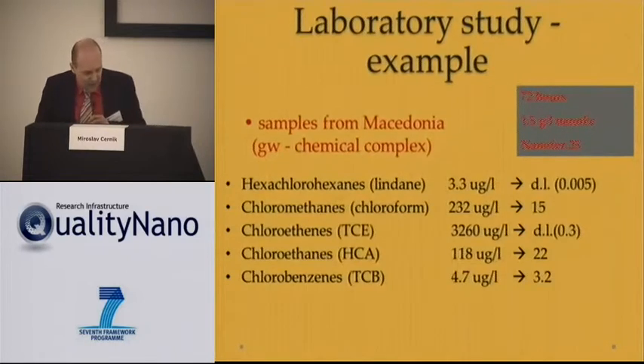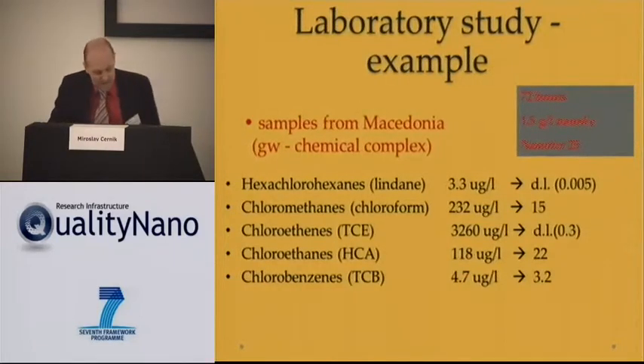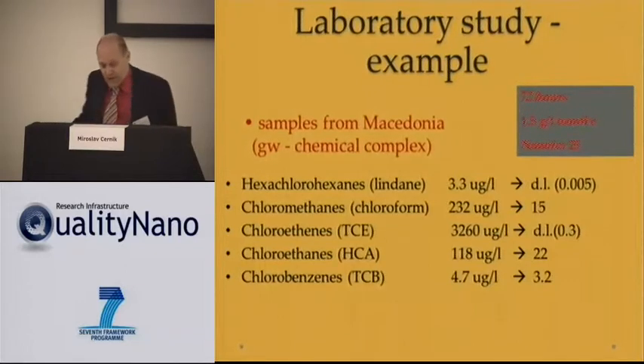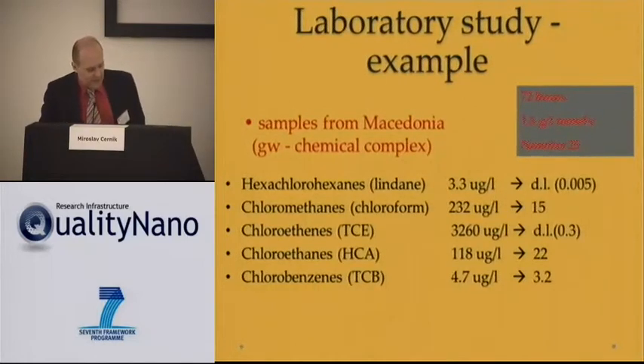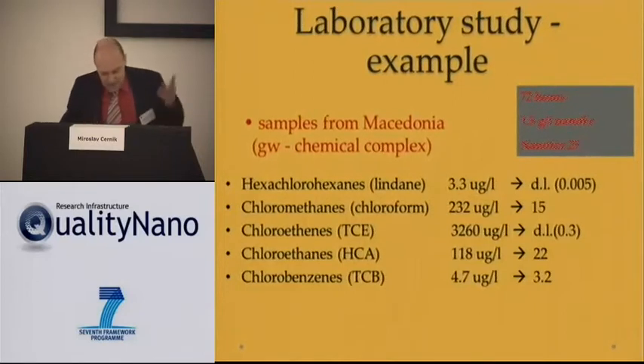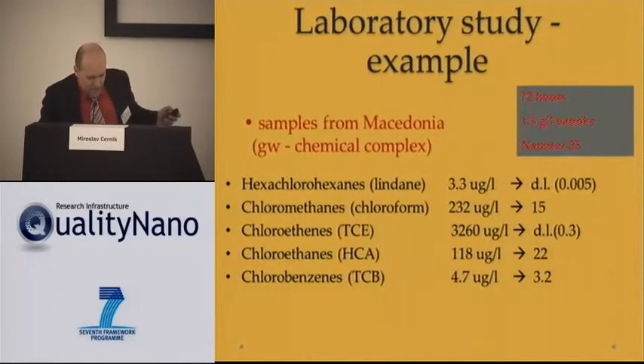We have here a small example from the laboratory. We had water from Macedonia, from a chemical complex where the groundwater around is very polluted by a really huge mixture of chemicals, from lindane to chloroform to chlorobenzenes, ethenes, ethanes, and so on. We treated such water in the laboratory for 72 hours with 1.5 grams of nano iron. And you see changes in the concentration, so that we are able to reduce the contaminants below the detection limit in most cases. So this is, let's say, a simple example of how this nano iron works in the laboratory.